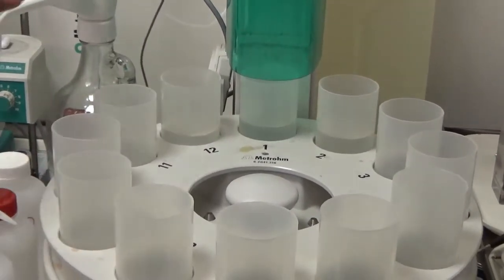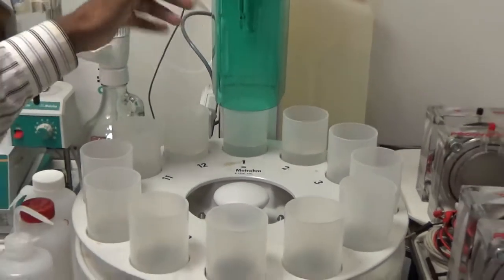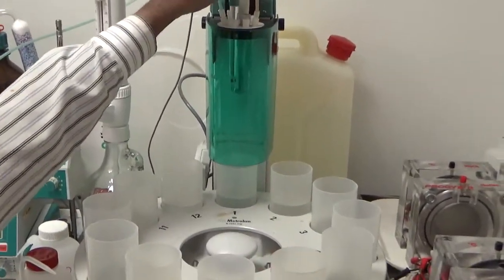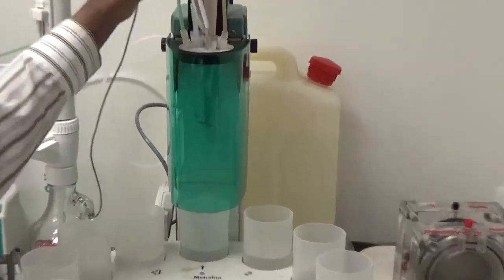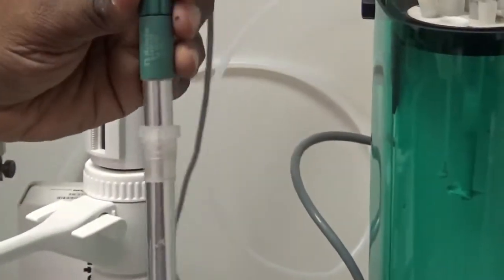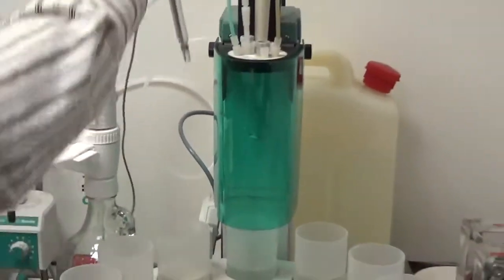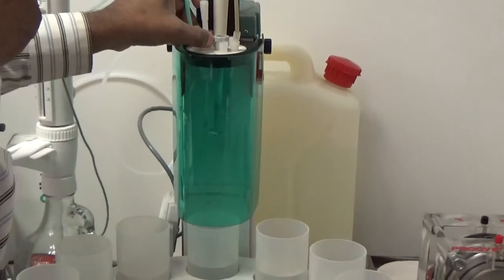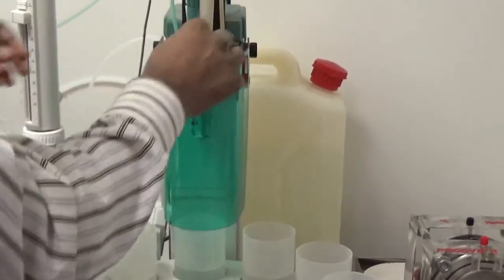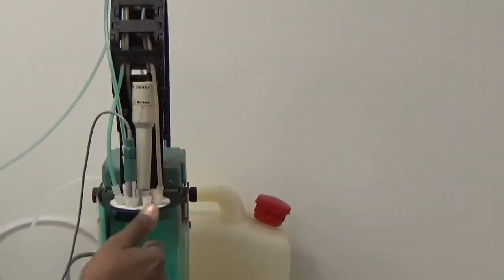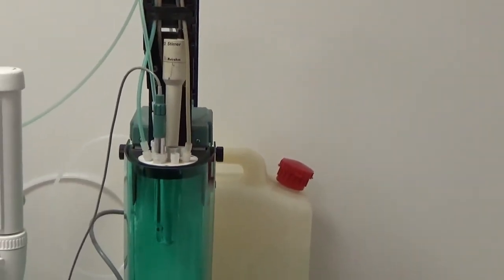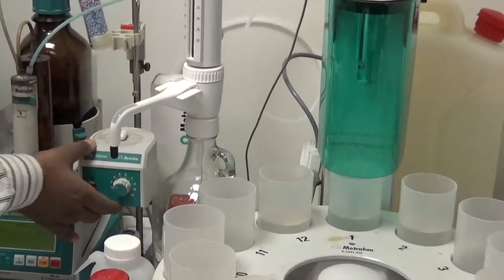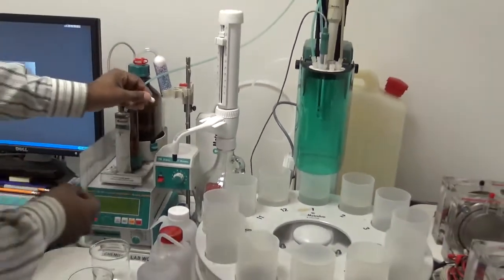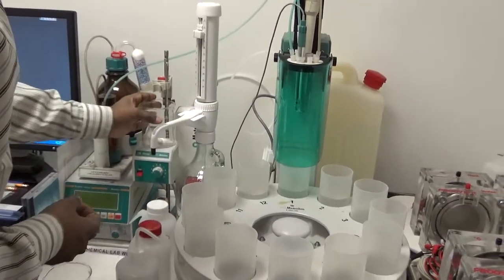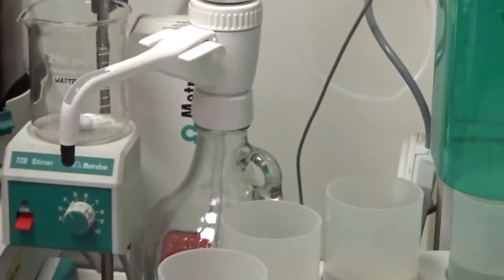Basically the column goes down with the electrode inside. We use a silver electrode to do the chloride analysis by potentiometric titration. This is a silver electrode, the metal electrode that we use. And this is the burette which goes inside. It also has a 722 stirrer. It's a rod style stirrer as opposed to the magnetic stirrer, which is 728. With a magnetic stirrer, you put a stir bar inside and it does the stirring. If I want to use the rod stirrer, then we use the 722 rod stirrer.